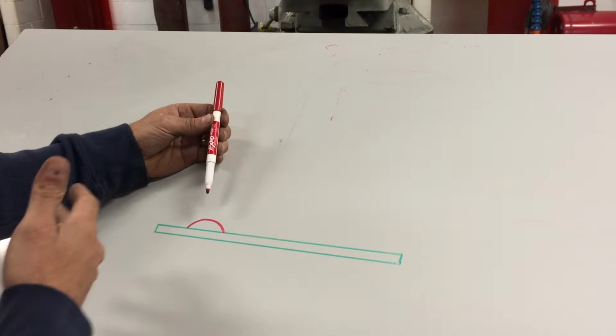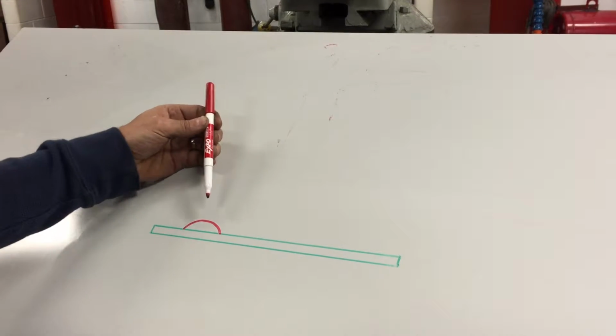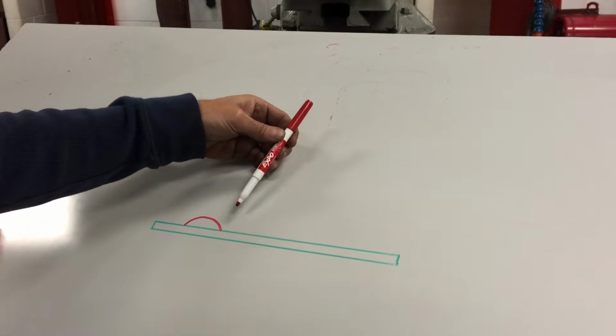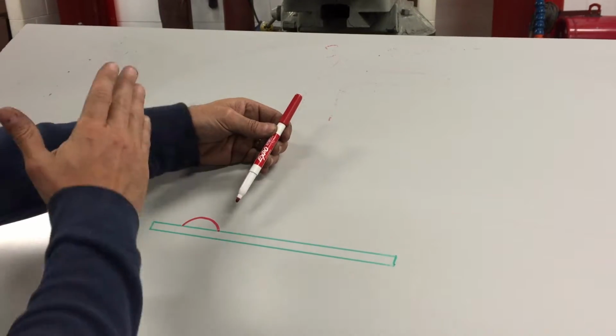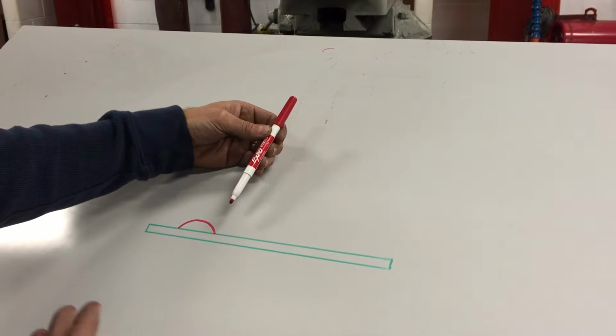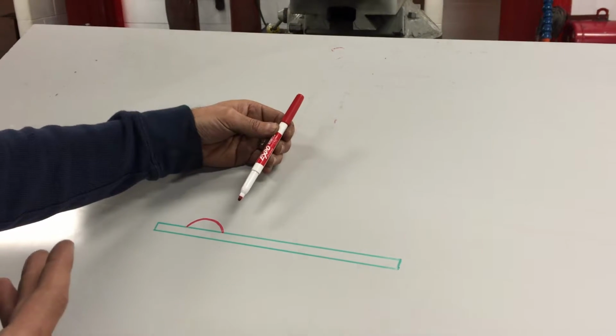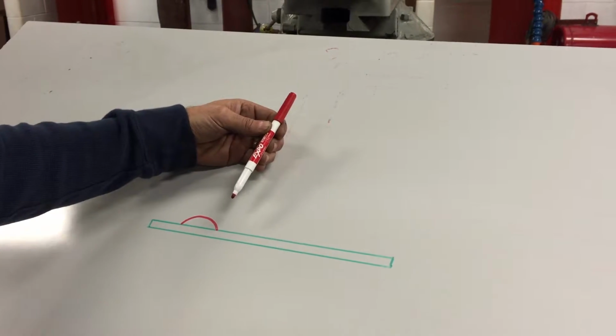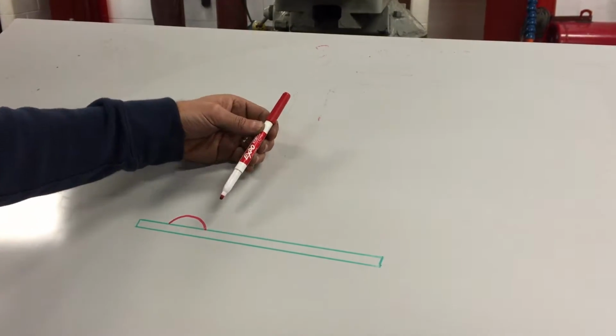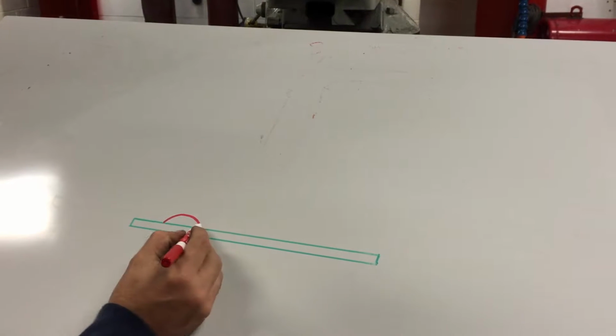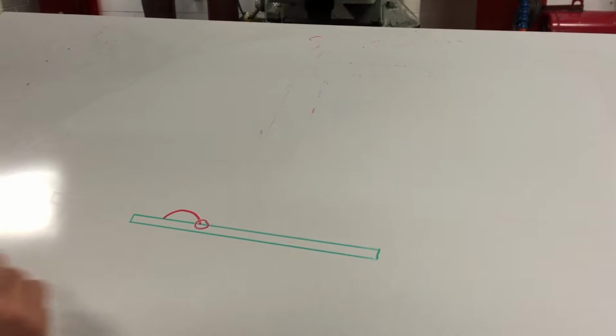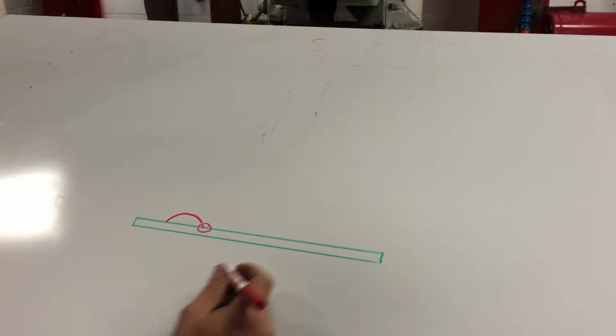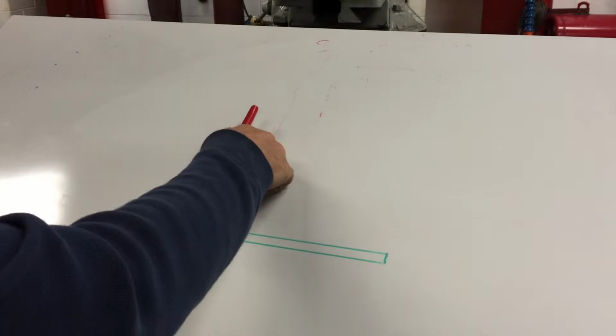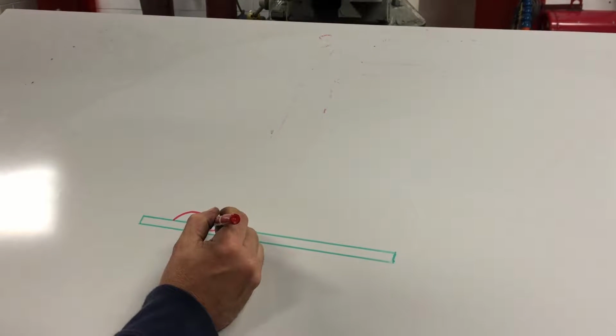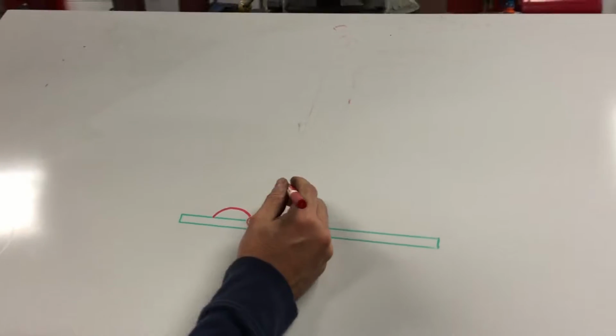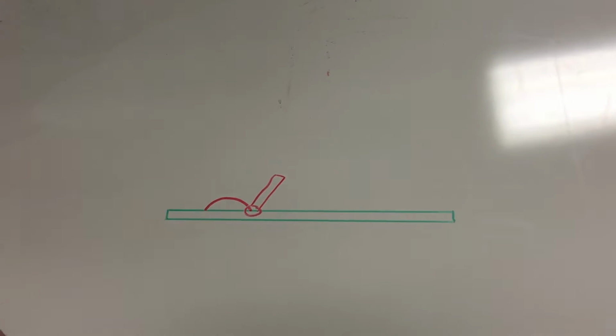Once we do that weld, we clean it, brush it. Then our welding rod will come over here. There's a little leeway for your work angle here. Somewhere between, I'm going to say somewhere between 75, 65 degrees, depending upon how you weld. Everyone is a little bit different. What you want to do, this right here, if you remember, is called the toe of the weld, where the weld meets the metal. So what we want to do with our next weld is our welding rod should come down and the center of the welding rod should cover the toe of the weld.